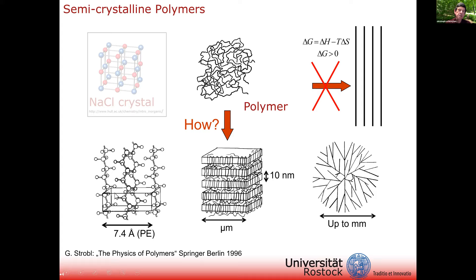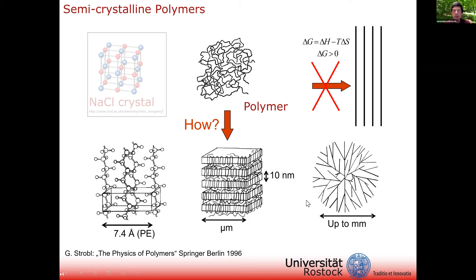This lattice structure is accessible by X-ray scattering. The lamellar stack structure is also accessible by small-angle X-ray scattering or electron microscopy. Spherulites, because of their size much larger than the wavelength of optical light, are also accessible by optical microscopy, particularly with polarized light. The way the polymer goes from the coiled conformation in the melt to this semi-crystalline lamellar stack morphology is still under debate. But I want to focus on the fact that each of these supermolecular structures, such as a spherulite, needs a primary nucleus to grow, and this primary nucleus is commonly just in the center of the spherulite.